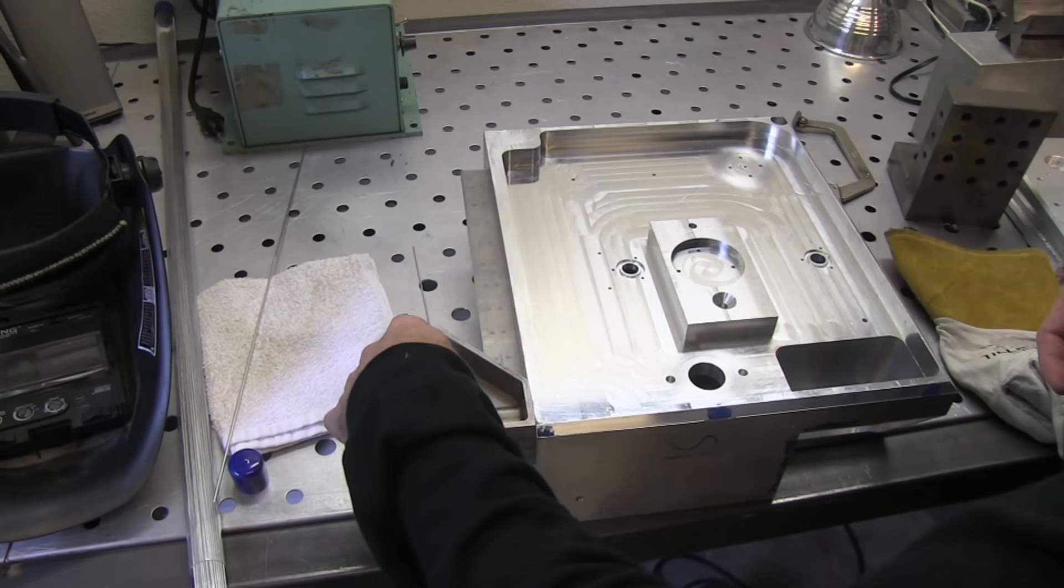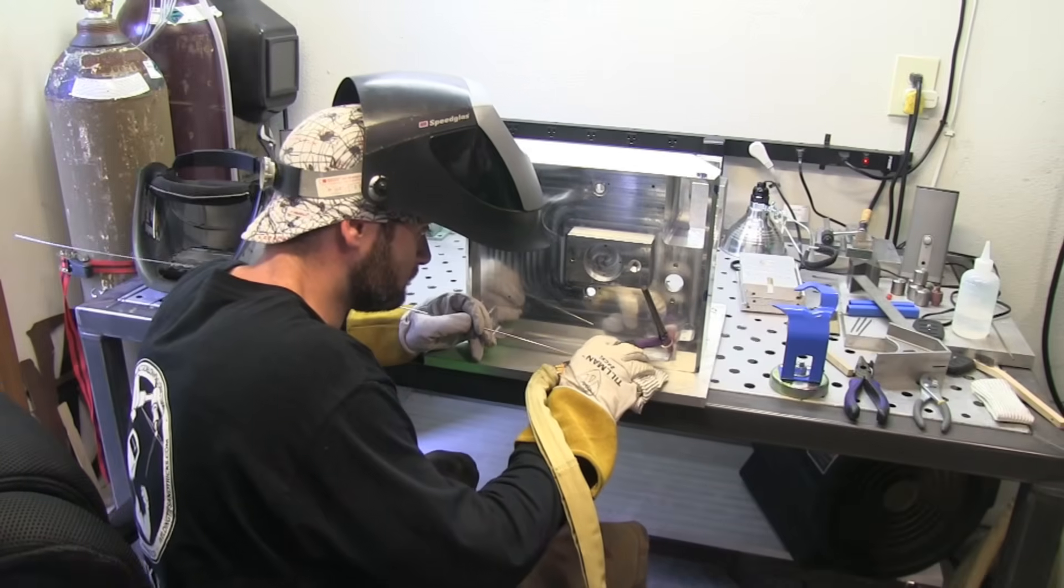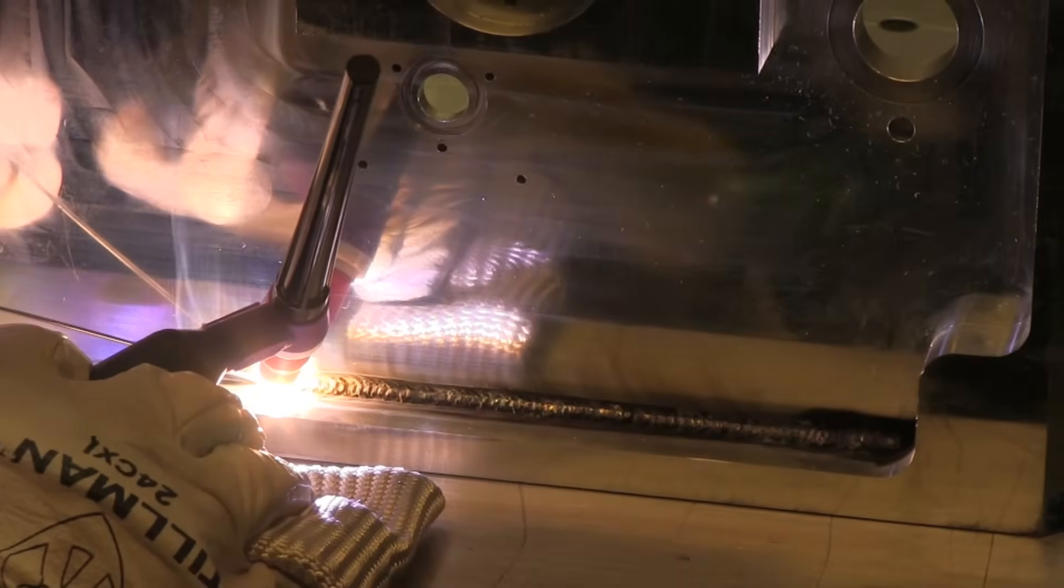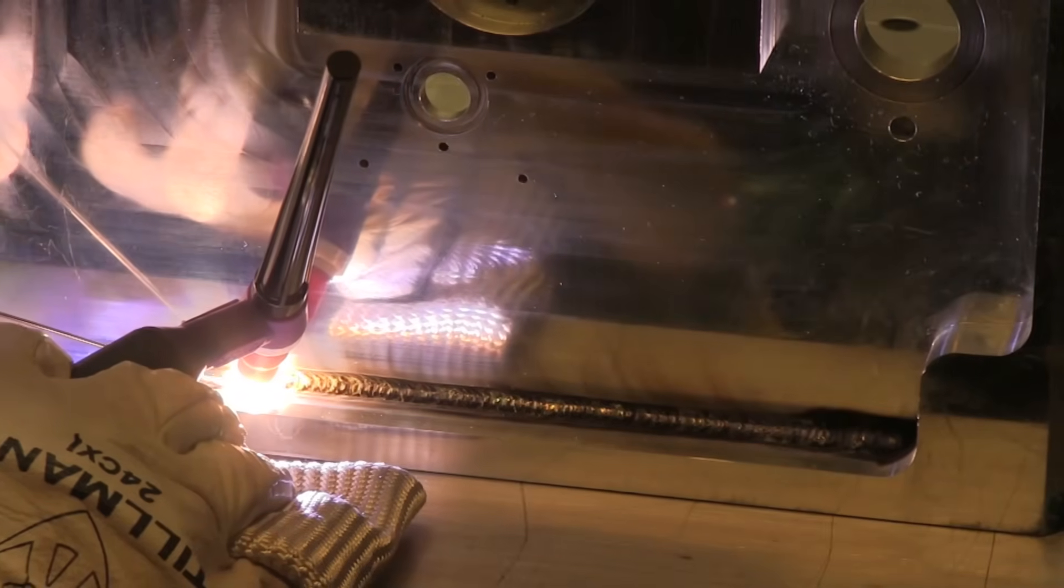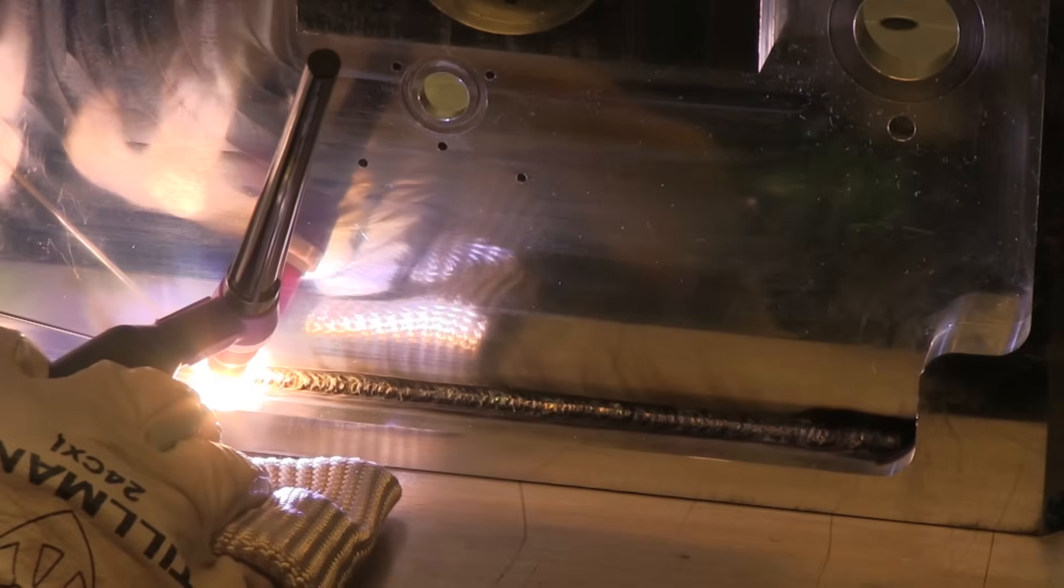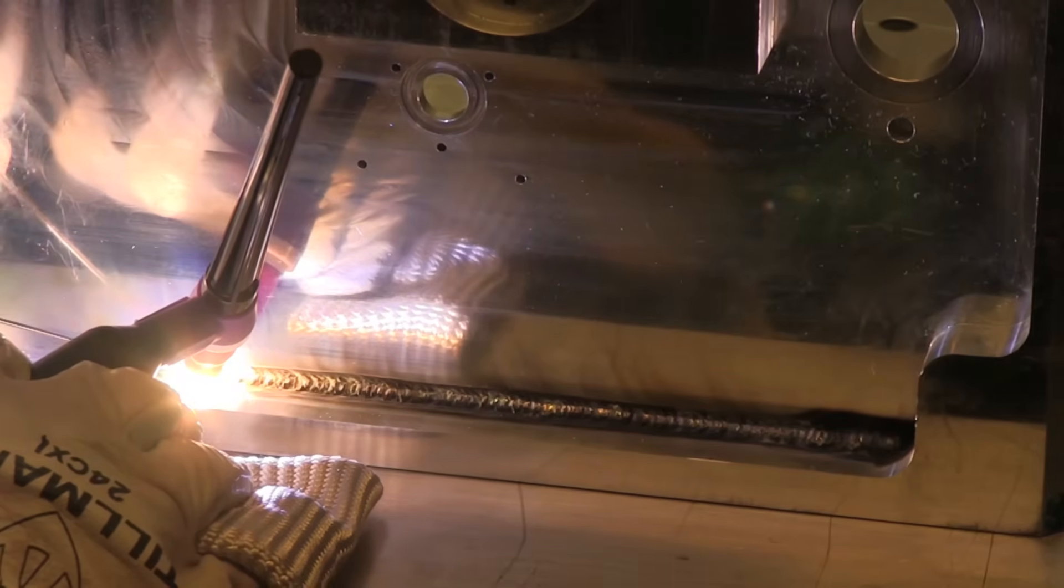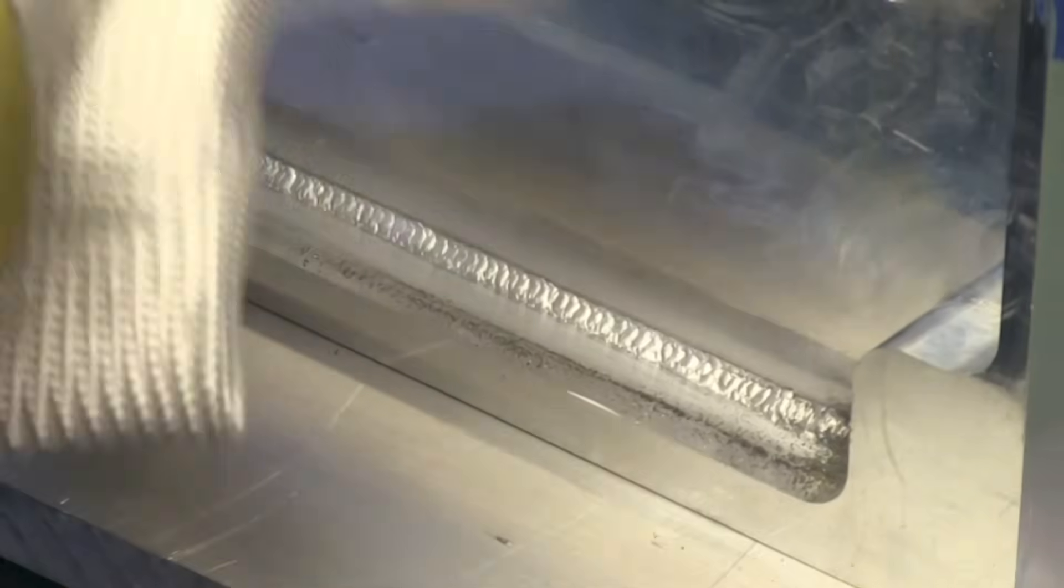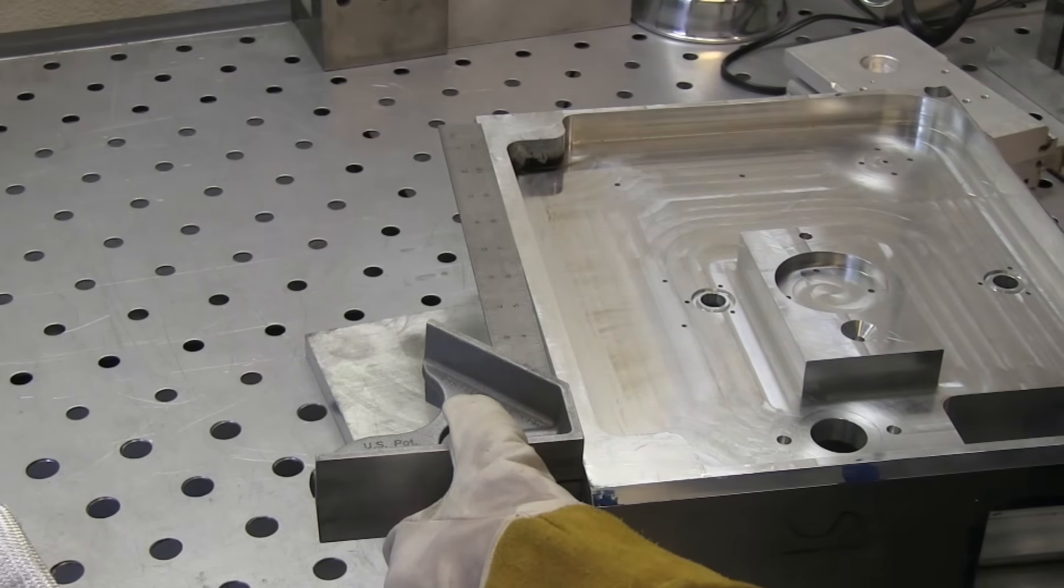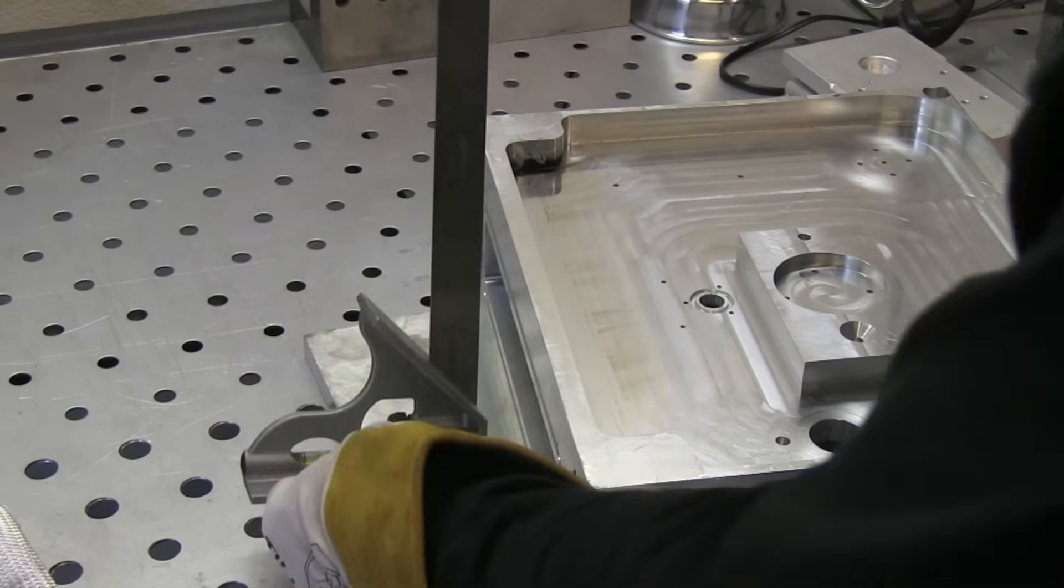Now we're going to check this before and after using a square here. And welding down this rail here where it's a corner and it's, I don't know, about three-eighths of an inch thick on the thin part. If you weren't careful using AC here and putting a big weld, you could easily draw that. You could bow it in and draw it over, but with DC, being able to pick up the travel speed, get the heat started, not have to wait on things to heat up, maintains flatness both ways.